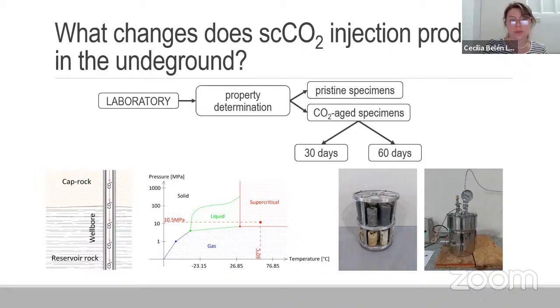In particular, we were interested not only in comparing the pristine and the carbonated sandstone, but also in observing the changes for different periods of CO2 aging. So in order to age these pristine specimens, we first obtained the specimens from outcrop, and divided them into two different groups.